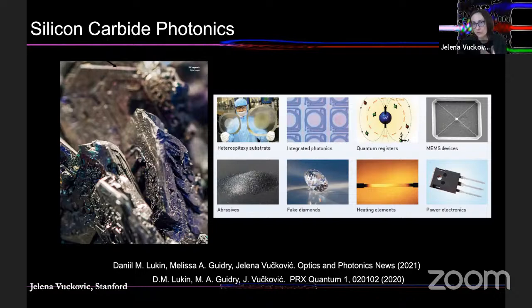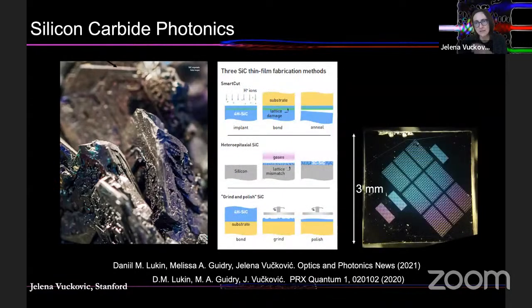guiding layer, right? You have to somehow produce your self-guiding layer because there is no thin film silicon carbide on insulator that is commercially available. And we tried a variety of things, but what worked the best for not affecting properties of the material and color center itself was bonding of silicon carbide wafer onto oxidized silicon substrate, and then grinding and polishing until you get rid of most of the silicon carbide. And then you have a thin film of silicon carbide sitting on insulator, typically few by few millimeter dimensions, but it's large enough to make a lot of photonics.